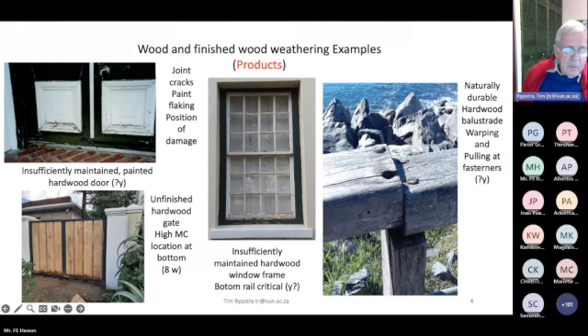Something perhaps more recent is an 8-week-old gate that was manufactured or installed, and you will notice at the bottom of the gate, after some rain, these darker marks show that there's more water at the bottom than there is at the top. Especially if this material is not treated with a water repellent, in other words, the end grain is not adequately protected, there will be capillary rise or capillary penetration from the bottom, in addition to water remaining there as a result of the larger amounts relative to the top. And then on the right hand side, a naturally durable hardwood balustrade, where you see the warping and pulling at the fasteners. Okay, the next slide, please.